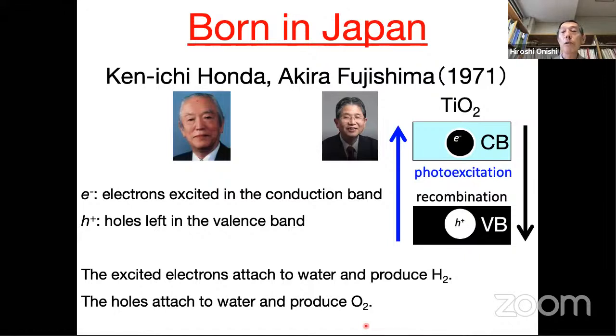This is the reason why we should find a good way to produce hydrogen. But when we use photocatalysis, even if we are interested just in hydrogen, we also have to take care of producing oxygen. If water oxidation to oxygen does not take place well, hydrogen production also does not take place. So we should take care of the pair of reactions, one reduction and the other oxidation. This is a very fundamental principle when we utilize photocatalysis for some practical purpose.